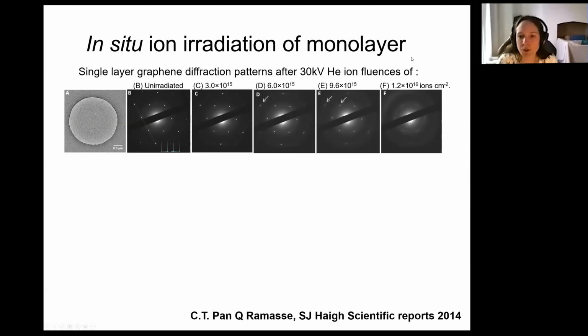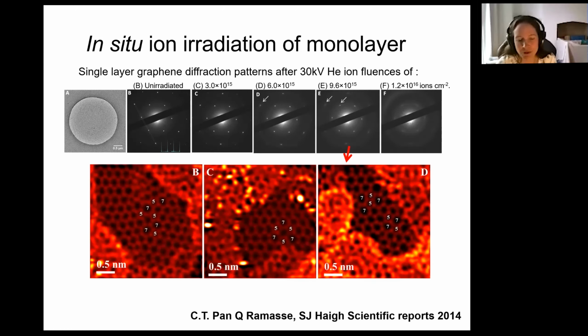And what we saw was when you get to these relatively high doses and you start to see streaking of these individual diffraction spots, we then took the specimen out of the MIAMI microscope, took it half an hour in the other direction to the ChemiSTEM facility in the UK, and Quentin Ramasse was able to sit with us over a few days and take hundreds and hundreds of images of 5- and 7-fold defects, which is how the graphene sheet is accommodating the damage due to ion irradiation. The ion irradiation is effectively knocking carbon out of the monolayer, and so the monolayer has to shrink to accommodate that loss of carbon, and you end up with these many defects, 5- and 7-membered rings. Okay.